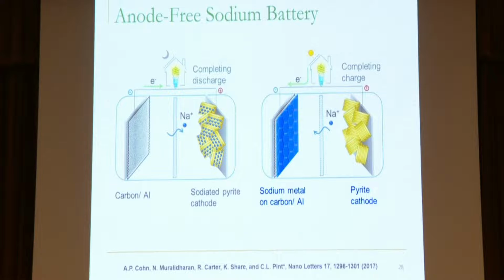So we made some batteries, and the way that we did this is we took this pyrite material, this fool's gold, we sodiated it, which means we stuck sodium into it to make it a cathode that contains sodium to begin with. And then what we did is we simply just charged it and discharged it back and forth. Took the sodium over here, plated it onto this carbon layer, and then plated it back over and over again. And that's how we charge and discharge our battery.